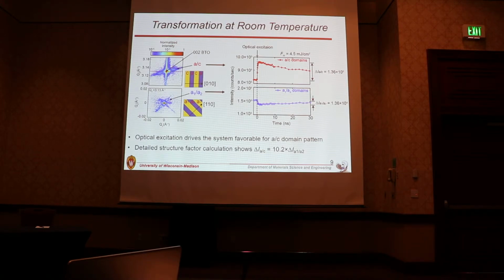different. But the X-ray amplitude is dependent on the structure of the domain patterns. We should consider the structure factor difference between the AC and AA domain patterns. Actually, we have performed detailed structure factor calculations and found that the AC domain pattern intensity changes should be 10 times larger than the AA domain diffuse scattering changes. So we can conclude that these intensity changes arise from the transformations from AA to AC domain patterns.